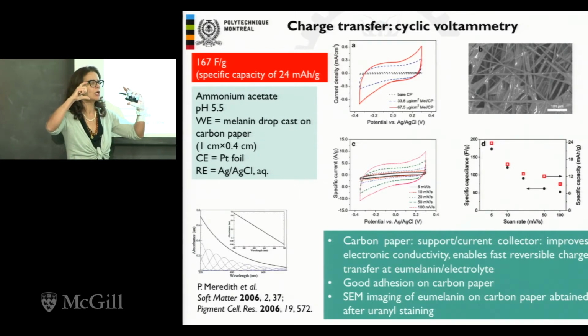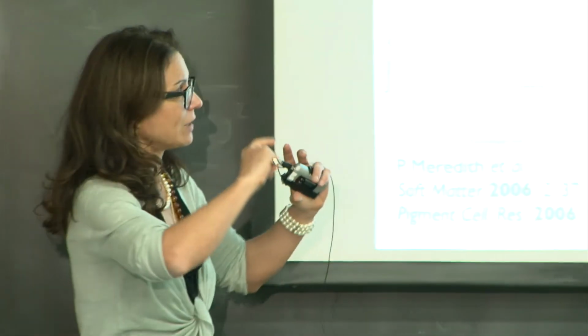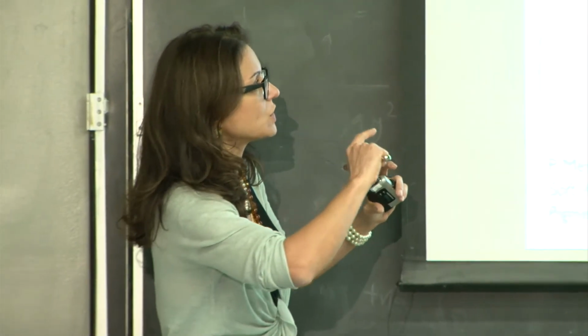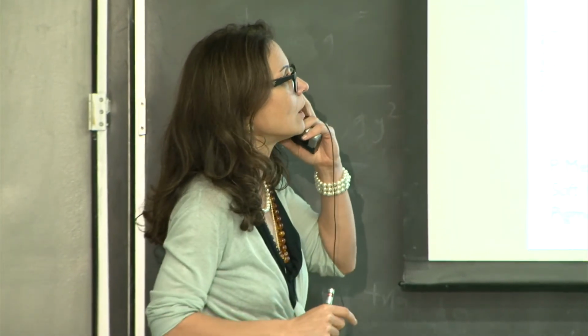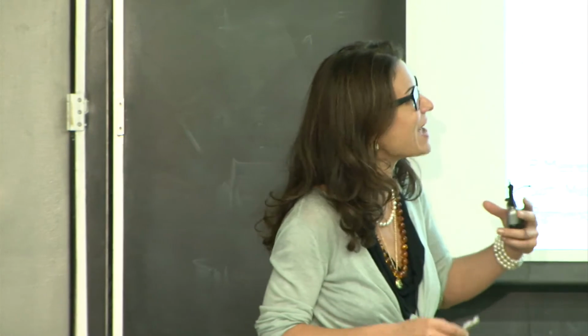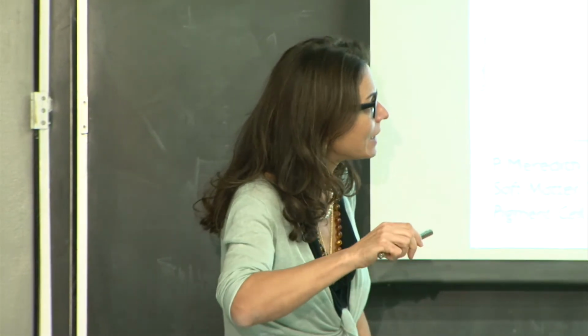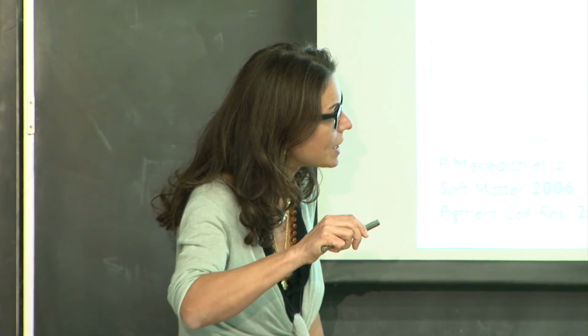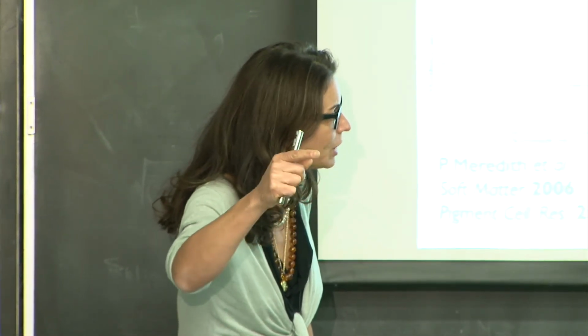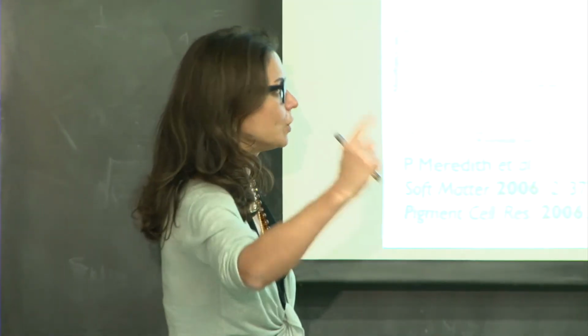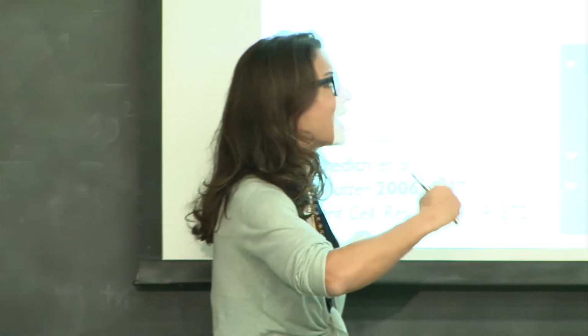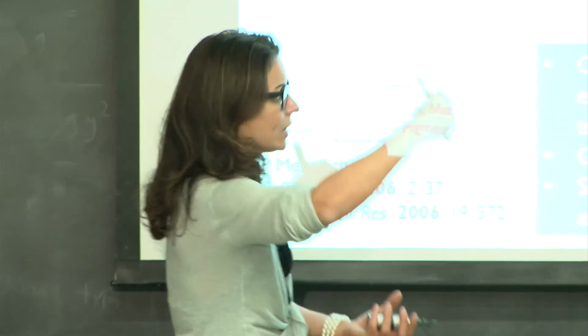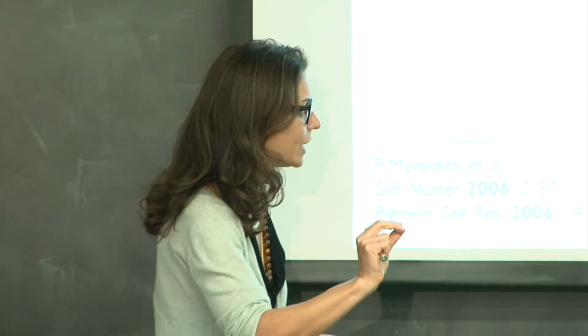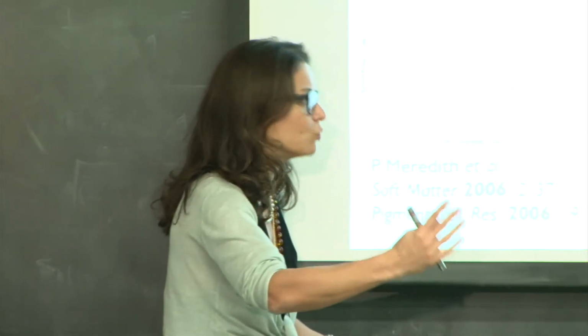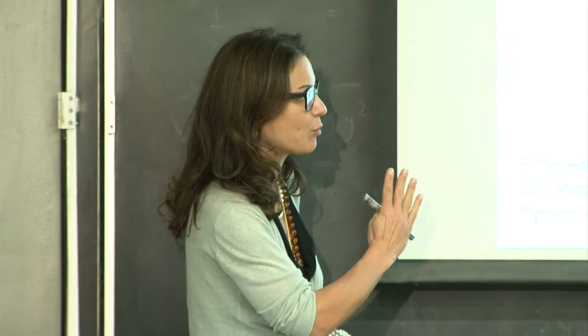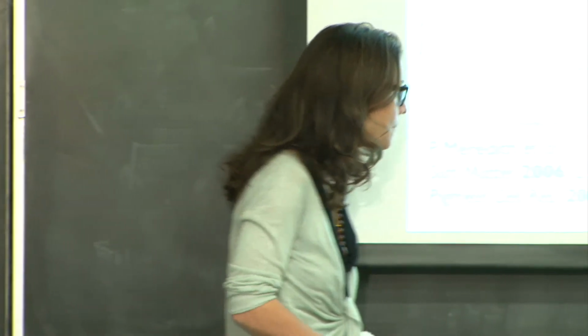So I don't store charge simply because of electrostatic effect, but I store charge because of redox processes beside electrostatic processes. So melanin behaves as a pseudo-capacitive material, and here with the increase of the sweeping rate, I prove the capacitive behavior. With the linear increase of the current with respect to the sweeping rate, we prove the capacitive behavior of our material. If we go into the interpretation of the results, it is actually, as I was saying, a pseudo-capacitive behavior. Faradaic processes take place beside electrostatic interactions, okay?